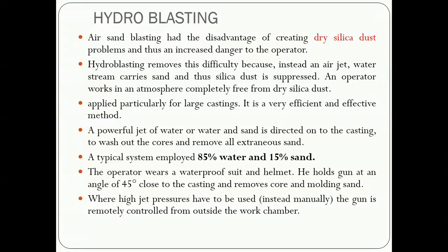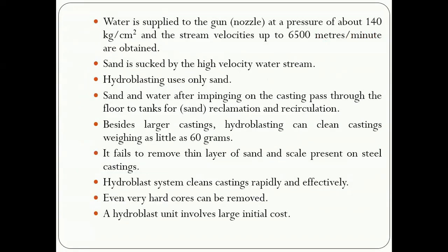This is hydroblasting. The water is supplied to the gun at a pressure of about 140 kg per centimeter square, and a stream velocity of up to 6500 meters per minute can be achieved by using this technique. Sand is sucked in by the high velocity water stream. The technique is the same.